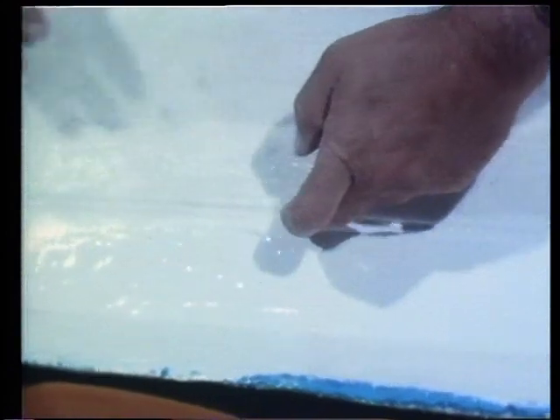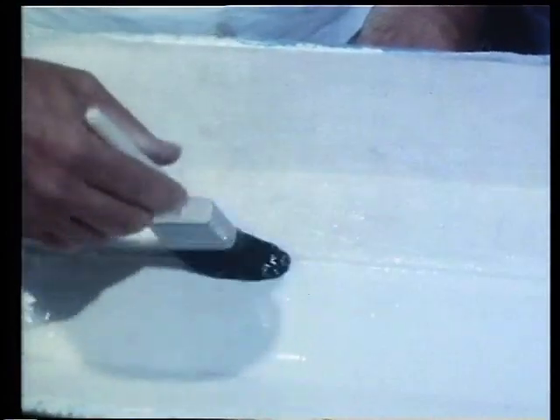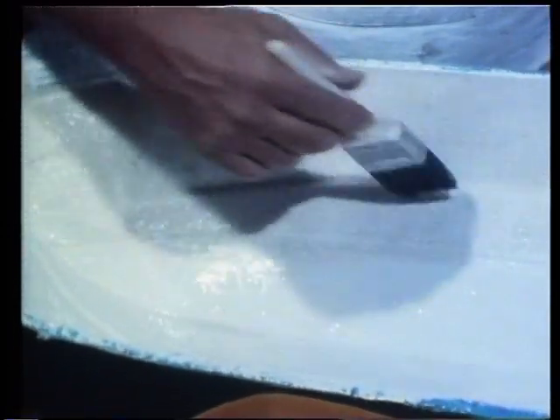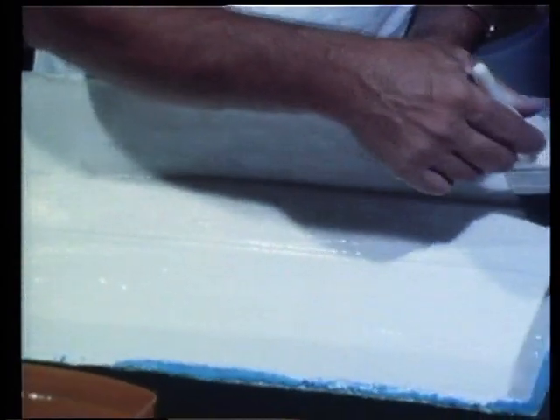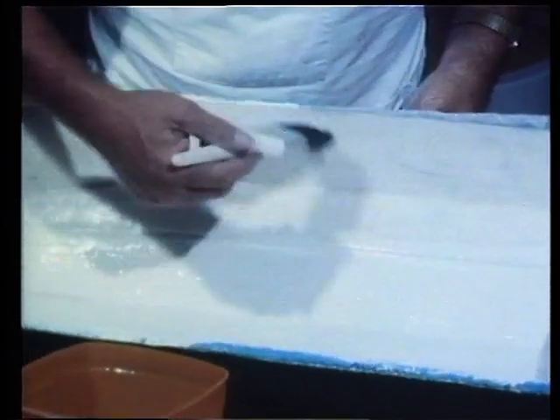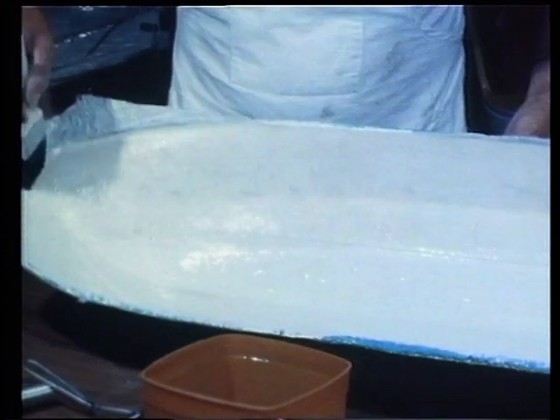Check over the back of the laminate. It all looks pretty good. And we finally tidy that up with a fairly dry brush. Again, the brush only has to be wet with resin so that it is effectively lubricated as it touches the mould surface there, rather than applying more resin. So we just use the brush for a final tidy up.